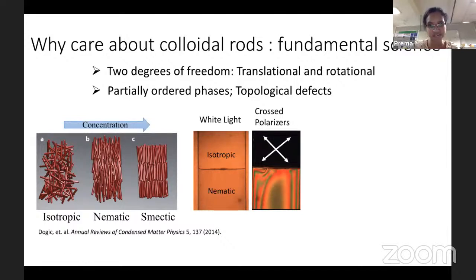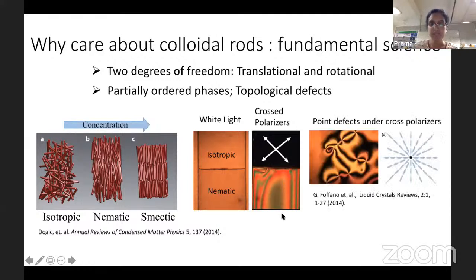So it has 2 refractive indices, one along the rod axis or the director axis and one perpendicular to it. So what happens is that when you pass linearly polarized light through a nematic phase, its plane of polarization gets rotated, and therefore you get some light on the other side. And then there is this idea of topological defects: within the nematic phase, you will observe what are called topological defects, where the director is not well defined. We will not go into the details of defects here, but I just wanted to bring that up in your knowledge.